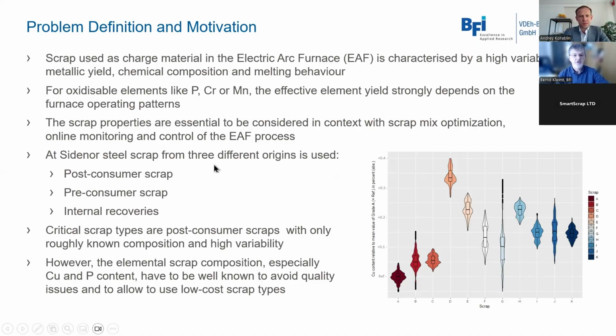At Sidenor, steel scrap from 3 different origins is used. The first one is the most critical one. This is the post-consumer scrap. This is scrap collected from scrap cars or scrapped household systems and so on. This is a scrap which is very difficult to characterize, and the composition of the scrap is only roughly known and has a high variability.